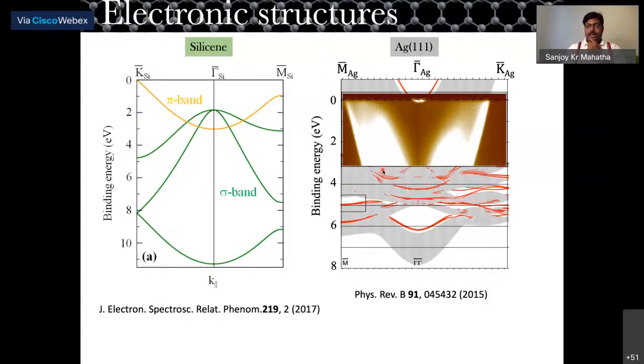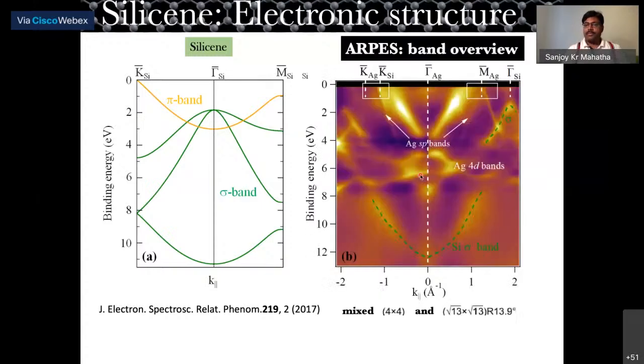And then if you put silicon on top, this is what we get. After putting silicon, we can see there are many different bands, like this parabolic band, which one can compare with the silicon sigma band. Then there are silver sp bands visible, like we saw before. But in addition, we also see some parabolic bands, like this one and these ones, and they are silicon sigma bands, basically the bands which we see here. But in this spectrum, we don't see any signature of a pi band. We don't see any band crossing the Fermi level with this kind of dispersion.